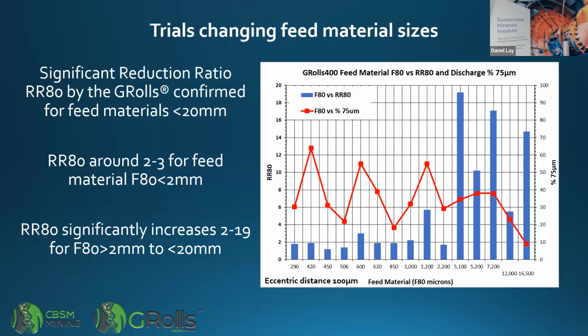So going through a whole lot of feed sizes, one of the things about comminution is trying to see how much your reduction ratio is, and the reduction of your particle size in a single pass. And so what we did was we plotted the reduction ratio here, on the left-hand axis in the blue bars.